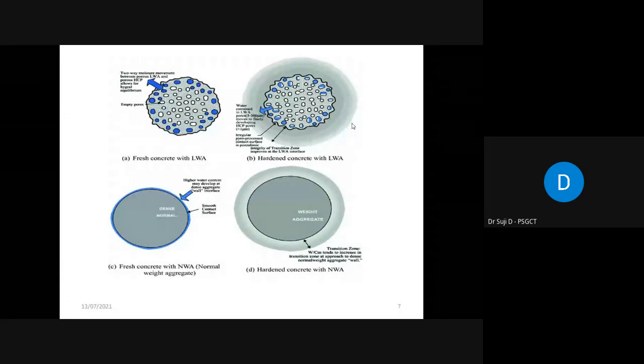So it is abbreviated as SAP, and shrinkage reducing admixtures, SRA, and sometimes wood powder is also attempted as a self-curing agent because it consists of some micropores on the surface, so that's a very good water absorbent, and it releases the water also, right? So lightweight aggregates including ceramsite, sometimes pumice, are normally used as self-curing agents. And the SAP, SRA both are capable of having high water absorption, more than 1,000 times their own weight. Imagine they absorb water more than 1,000 times of their original weight.